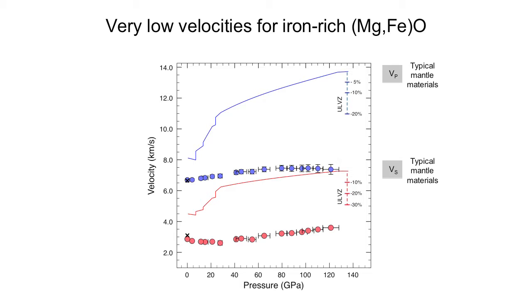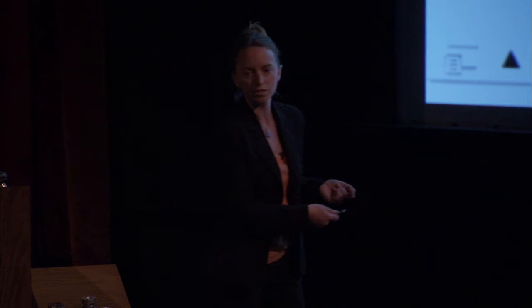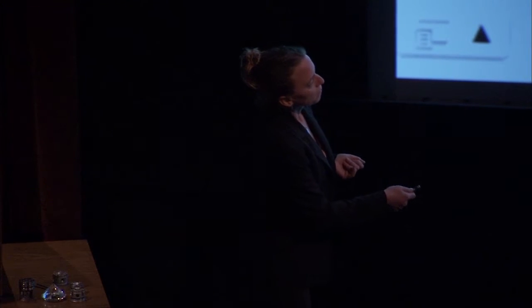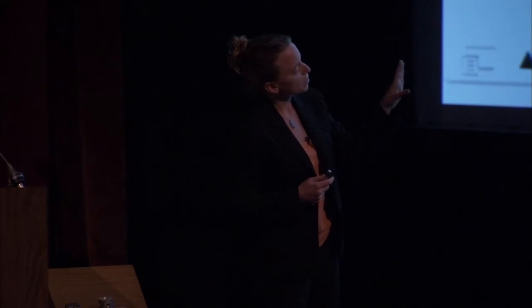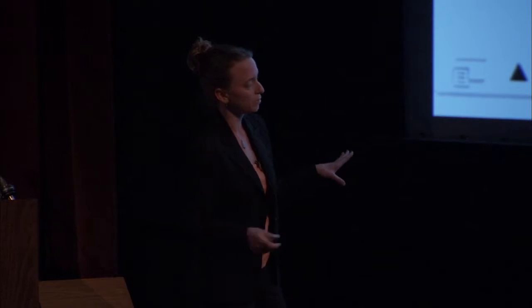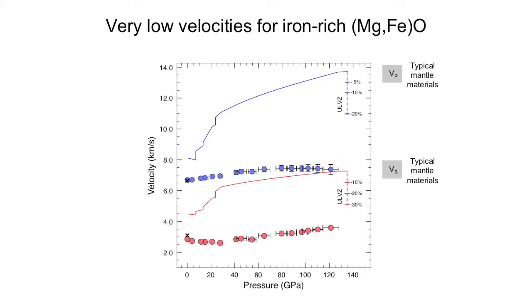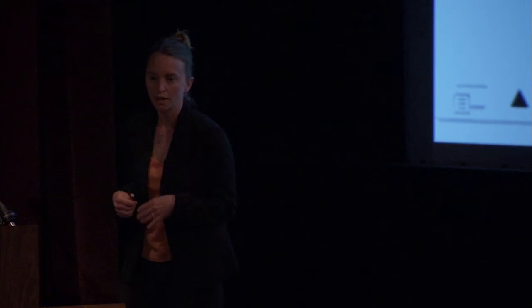And now we can see the same drastic phenomena that happened in the shear wave in this material. And we see decrements of seismic speeds, just how low they've observed seismic wave speeds. So if we look at these measurements, we see that these measurements were done without even heating the sample. So this is a solid phase that is characterized by extremely low vibrational properties. And if we heat this up, it probably will get even lower. So we only need probably a fraction of this material to explain the seismic observations.